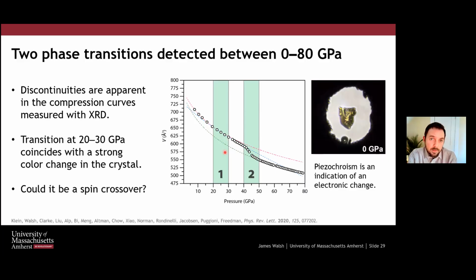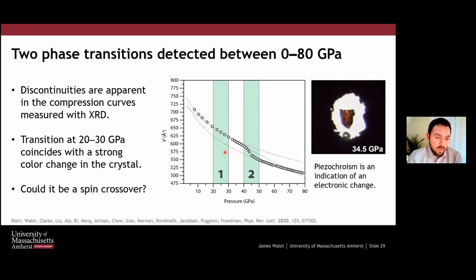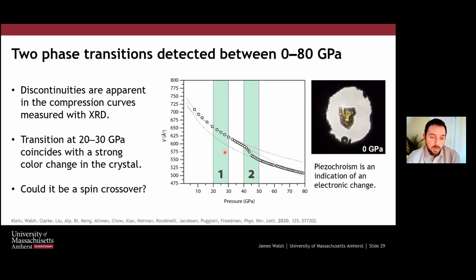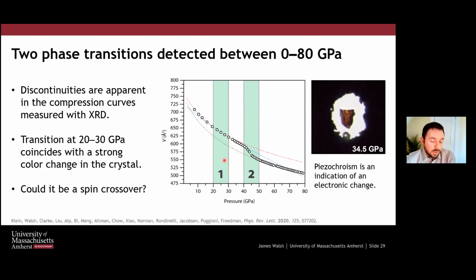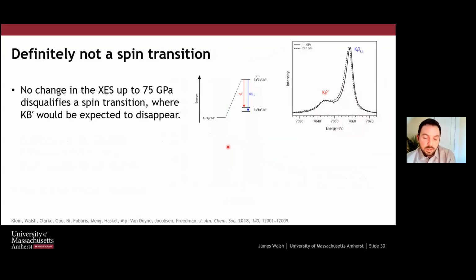And so we wanted to investigate what was the cause of these, and always in the back of our mind, we're hoping it's a spin crossover, because then that might mean we have spin 1/2 ions on a kagome lattice. So the transition at 20 to 30 GPa, which we're showing in this animated GIF, we see a color change. This is piezochroism. As we compress the crystal, we see it change from yellow to red. And so at first we were hopeful, maybe this is a spin crossover. It wasn't.